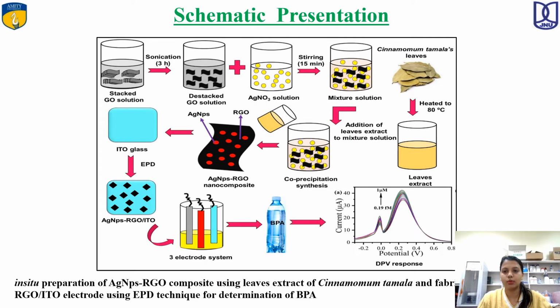So in the proposed work, I have used a sensor in which one component acts as a receptor as well as a transducer, and we have synthesized an in situ nanocomposite using two nanomaterials, that is silver nanoparticle and reduced graphene oxide. We have reduced it using the plant extract of Cinnamomum tamala, which is usually known as Tej Patta or Indian bay leaves, and then fabricated the nanocomposite using the electrophoretic deposition technique on an indium tin oxide glass plate for determination of BPA. This is a whole scheme showing the synthesis as well as the fabrication process.